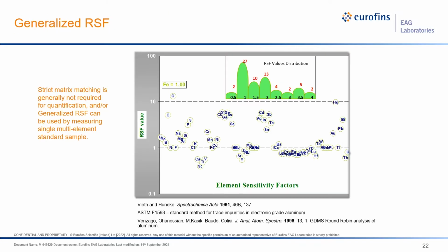Here are more details on this generalized RSF set. In GDMS analysis, strict matrix matching is generally not required for quantification. If the relative sensitivity factor of iron is set to 1, you can see that more than 50 elements have RSF values between 0.5 and 2, with the remaining 10-ish elements between 2 and 4. Thus, generalized RSF can be used by measuring a single multi-element standard sample, and with that, we can do full survey analysis for even materials without strictly matching standards.